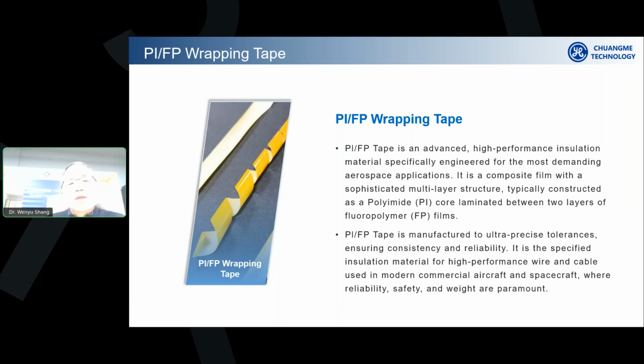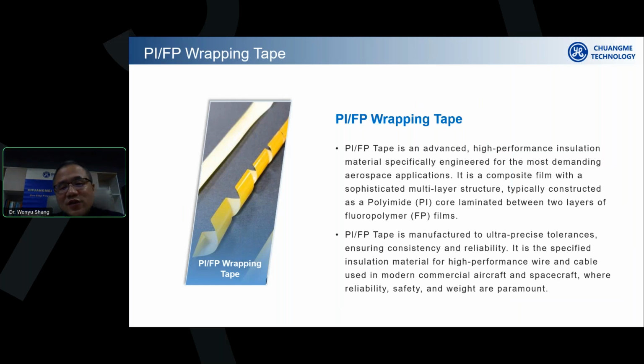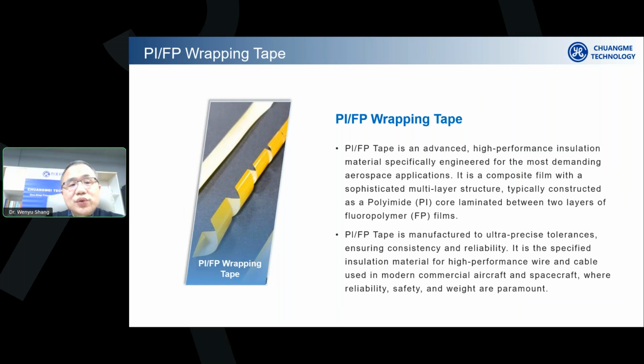And at the same time, these two layers of fluorine polymer coating on both sides are in contact with each other in the wrapping overlapping area, and then they would melt and form a continuous insulation layer. So through this design, we can produce a high temperature resistance aerospace communication cable, and make the wire sustain a very high temperature working environment.